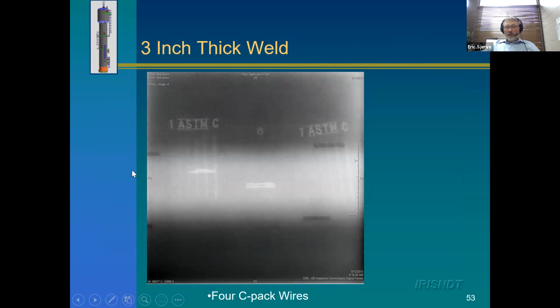And then this is another one I throw on here. This has a C pack because it's a thicker weld. In this case, this is the base material, which is darker. This is the weld reinforcement, which is white because it's a thicker material, which means less radiation gets to the film. And this is actually, we've cut notches in this to be a UT calibration block. And these are tungsten rods in the middle of the weld for a UT calibration block.